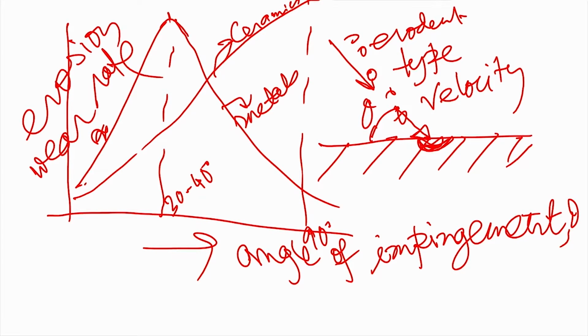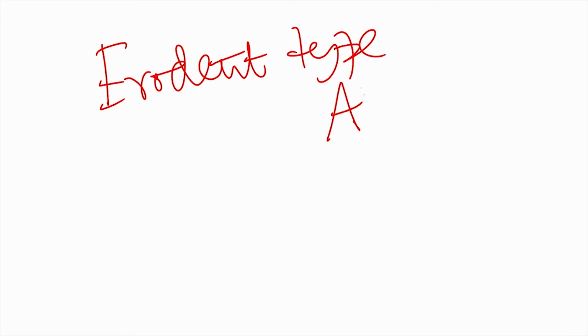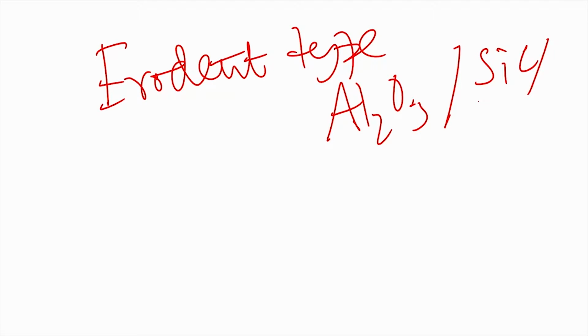Although people do vary the angle of impingement, if you want to do very limited experiments and just assess the performance under the most aggressive erosion wear conditions, then I would suggest you do it where the wear loss is maximum. So, what are the different parameters that are important? The erodent type: typically, the erodent is either alumina or silicon carbide. This is the most commonly used erodent.